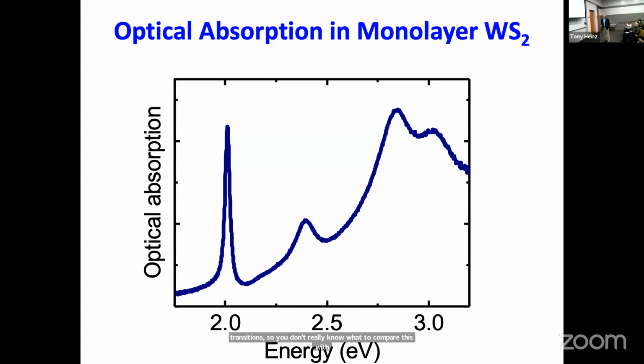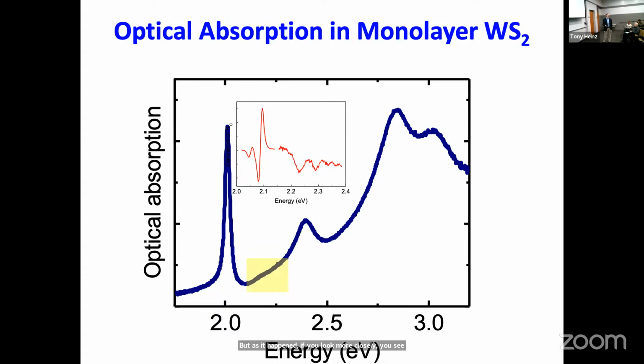But as it happened, if you look more closely, you see down in this region that there actually are some higher lying excitonic states. So just as in atomic spectra, you have the lowest transition, you have higher lying states. And those could be extrapolated to the ionization energy. So this told us that the exciton binding energy was several hundred millielectronvolts. So obviously not as strong as binding of electrons in atoms, but much stronger than you normally see in bulk semiconductors. And in particular, it means that all these excitonic effects are dominant at room temperature, not only at low temperatures.